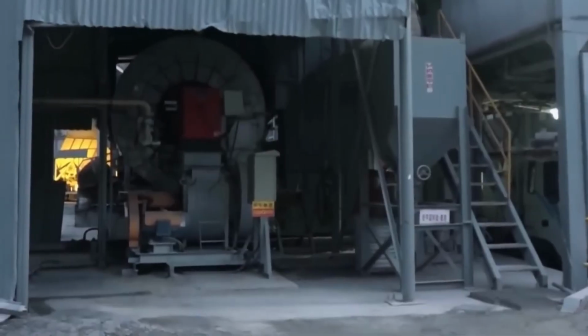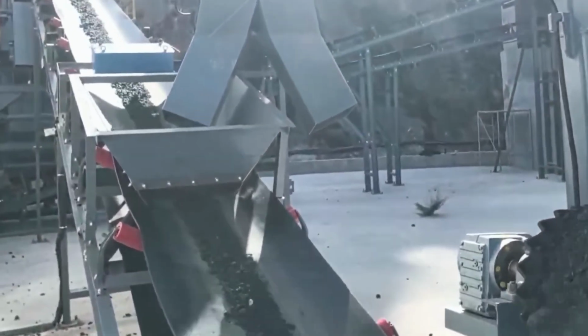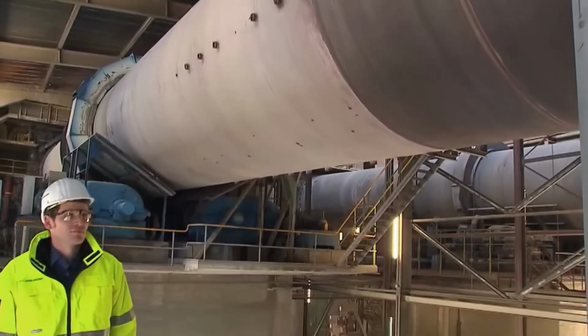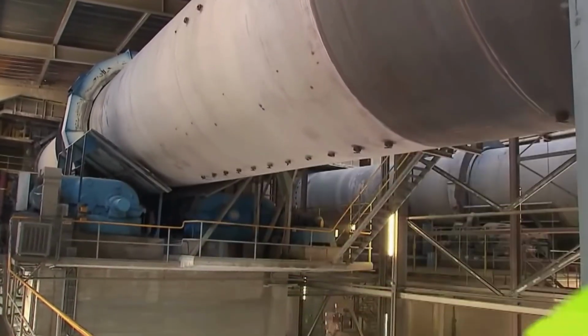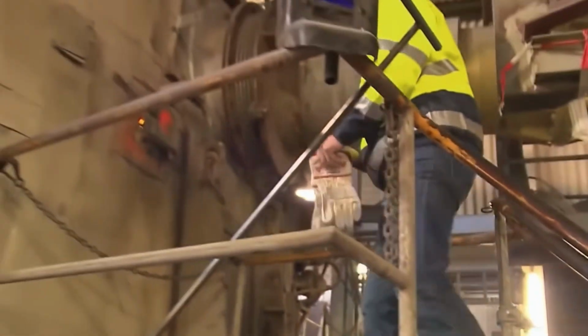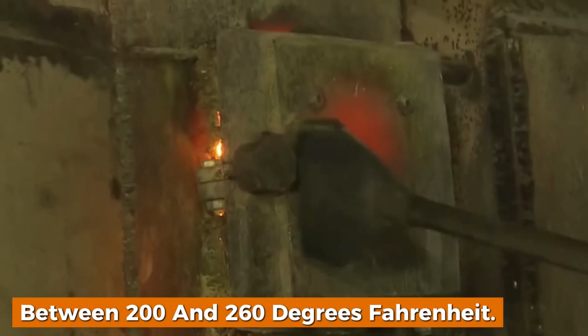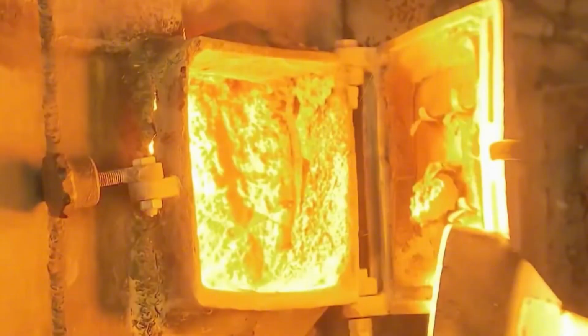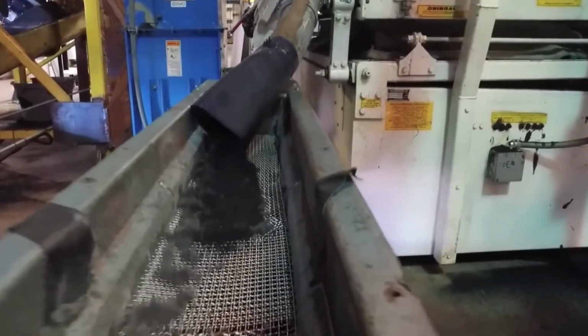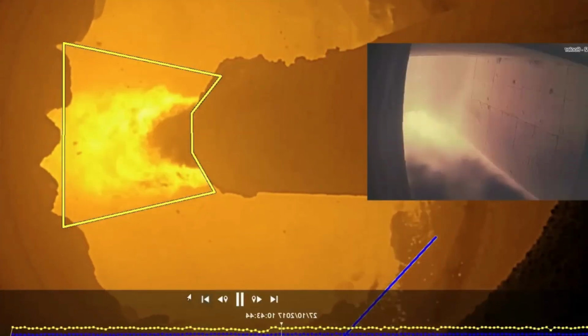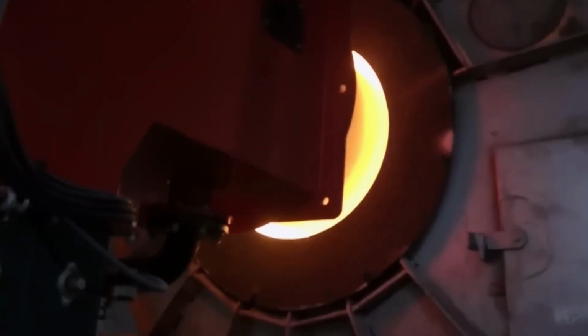Inside the plant, rubber granules are fed into a rotating drying drum, a large steel cylinder set on a slight incline and kept in constant motion. Hot air, produced by burners fueled with natural gas or fuel oil, flows through the drum at temperatures between 200 and 260 degrees Fahrenheit. As the material tumbles, moisture is gradually removed and the surface of each rubber particle becomes dry and chemically active, ready for interaction with bitumen.